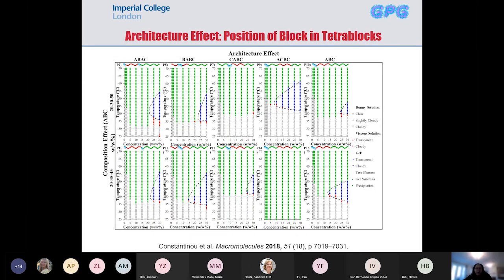So our results, again, were the same in the sense that the ABC architecture seemed to be the best in this case. The composition was slightly different, so our ABC was this one, where we did find, again, that we are at 37, we do have a gel, but as I said, we wanted that to be a bit lower. The two promising ones in terms of the tetrablocks were the ACBC, so the B block is still within the middle of the polymer chain, but not quite in the same way. And again, here we still have one part of the B in the middle of the chain.